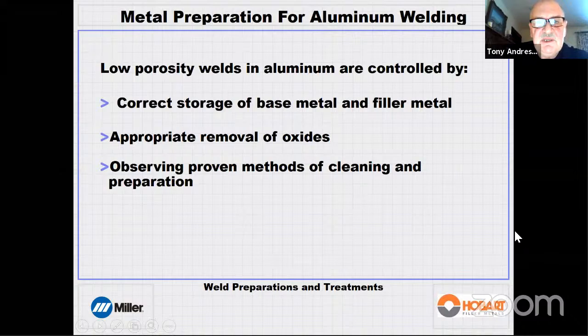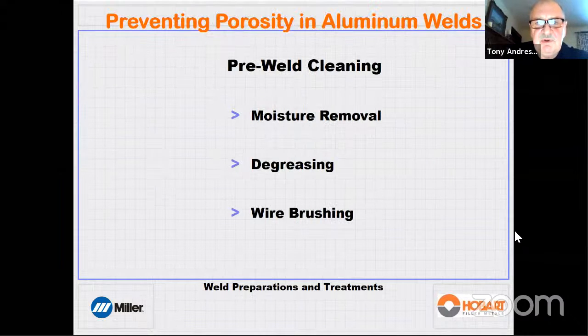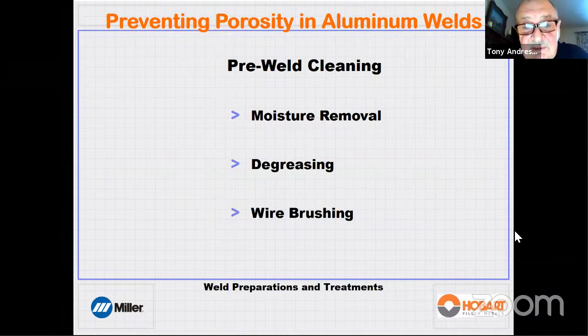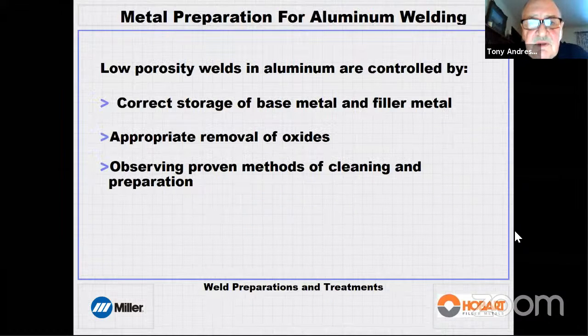All right, we'll go through all these. Moisture removal, degreasing, wire brushing. So pre-cleaning: if you want X-ray quality welds, not just high quality welds, you really need to take pre-cleaning really, really seriously. The best people out there that are turning out the best aluminum welds pay much attention to the pre-cleaning methods, storage and pre-cleaning. And usually it's moisture removal, degreasing, and wire brushing in that order. Correct storage of base metals, appropriate removal of oxides.